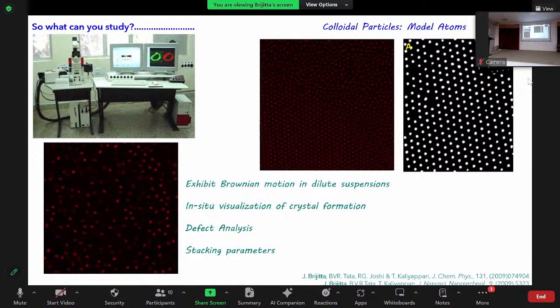And so in this picture also, these are only pseudo colors which you are seeing here, which are just coming because of the dyes, and here you are also seeing the grayscale image. And we can also study a lot of solid state chemistry. You might have studied about point defects, stacking faults, and also if you see, this is another stacking fault, where you can see the plane is continuous here, and so you have a fault coming here. So this is kind of Y defect, and you don't have any particles here. So these are the point defects. You can study all atomic phenomena like Schottky, Frenkel defects, but on a larger scale using colloidal systems.